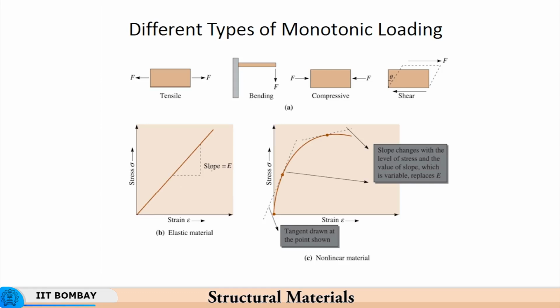When we looked at how interatomic distance is determined, the interpotential curves, what we had said is that the curvature at the trough of the interpotential curve is proportional to the Young's modulus. So, not the radius of curvature, but the curvature at the bottom. If the curvature is very sharp, the Young's modulus is very high. So, the smaller the radius of curvature, the greater the Young's modulus. So, the interatomic arrangement has a very significant effect on the Young's modulus that is observed.